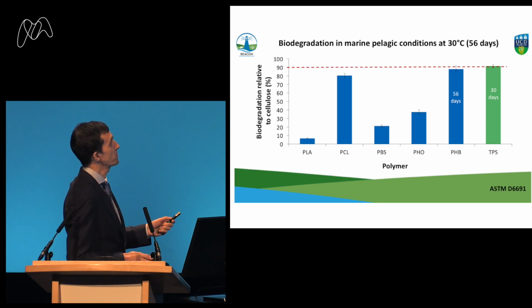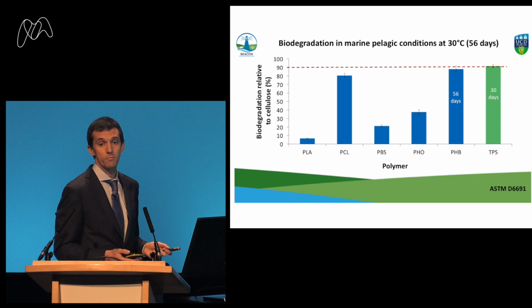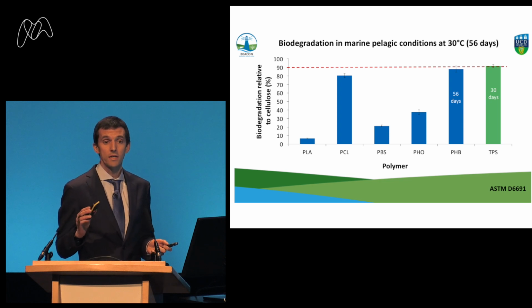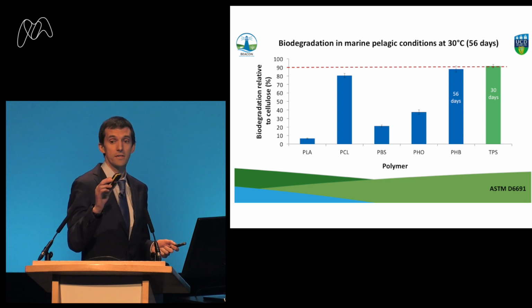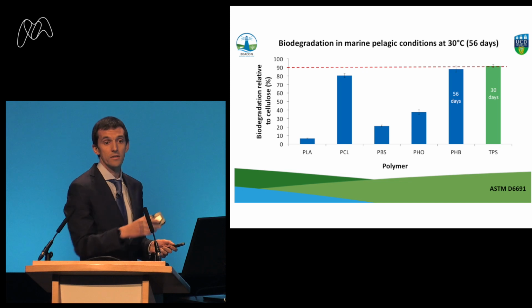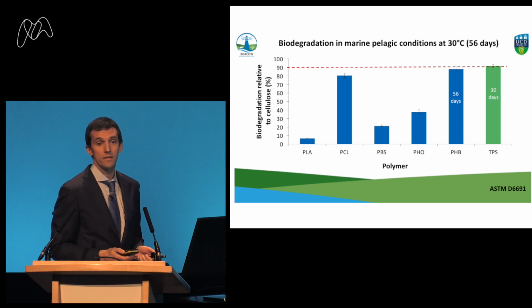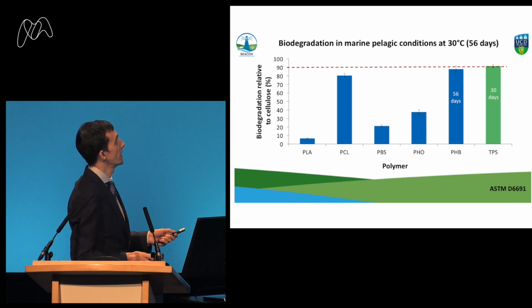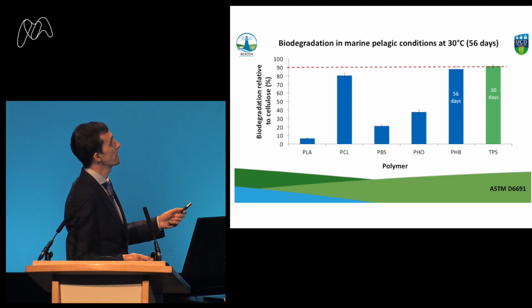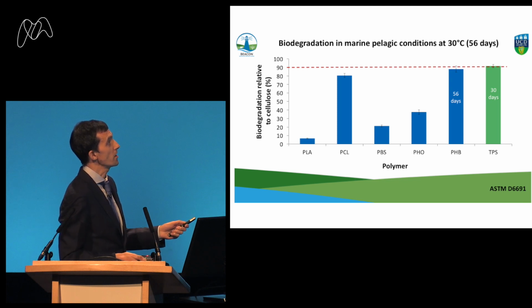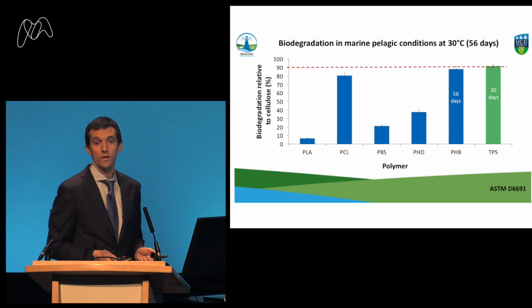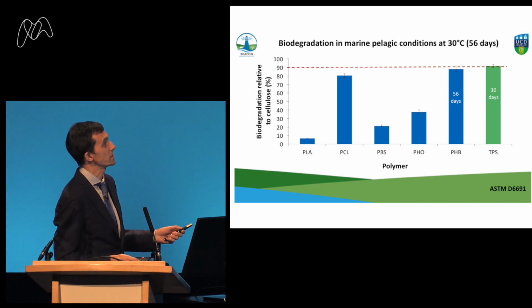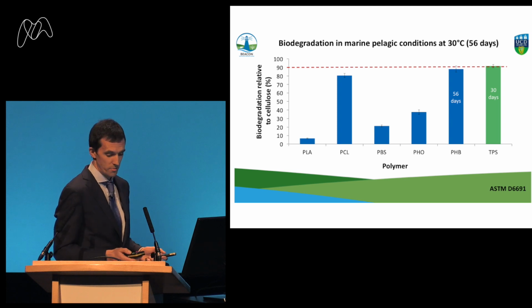And so again, what you see is PLA is a very poor performer. It's around 6%. As a matter of fact, you see rapid 6% degradation at the start, and then it flatlines. So we would argue that PLA, once it gets into the ocean, will last as long as any petrochemical plastic. PCL nearly makes the standard, but not quite. PBS, PHO are poor as well. PHB almost there, and TPS was the only one that made it over the line, and it degraded in 30 days, so your starch-based plastics.